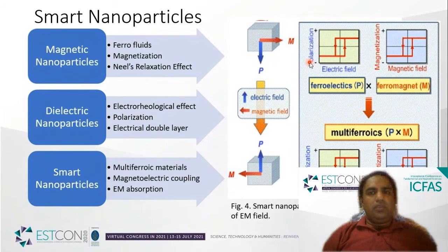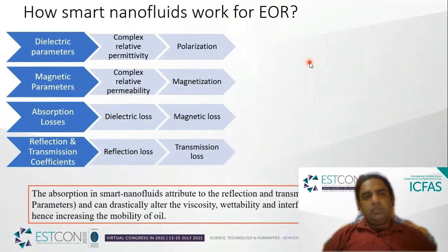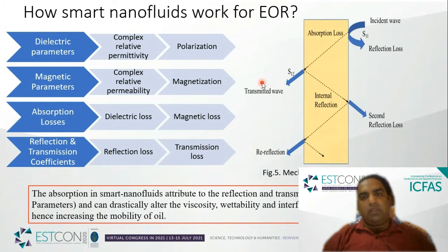So as we know, an electromagnetic field is a combination of electric and magnetic components. So we can use this electromagnetic field to change the direction of the domains and also the direction of the dipoles. So these smart nanoparticles, or nanofluids, actually change the dielectric and magnetic parameters in the reservoir. They change the polarization and magnetization properties. And at the end, when we apply some electric field, there is some increase in the absorption loss due to the internal reflection.